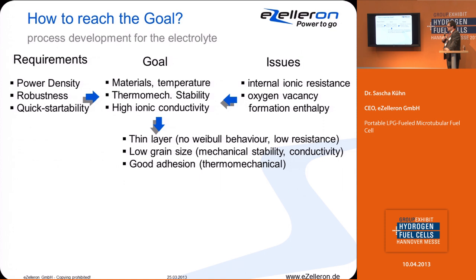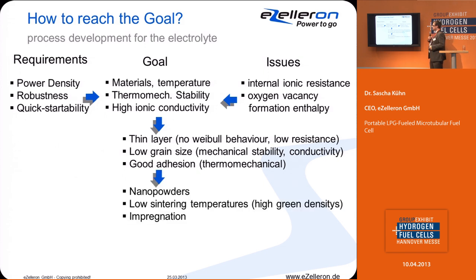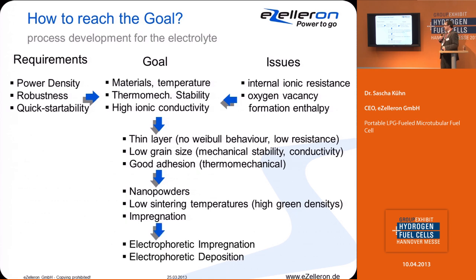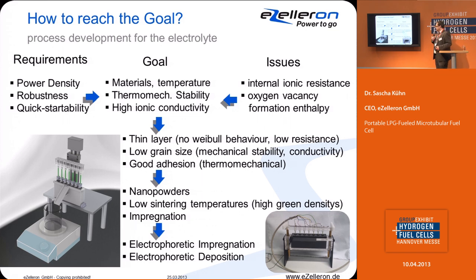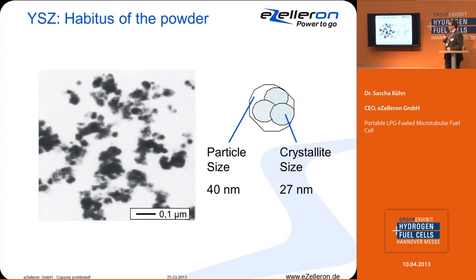The next thing is that for this thin layer you need a very low grain size to improve the mechanical stability. The conductivity of the layer also improves by that, and furthermore you need good adhesion of that layer, because otherwise the layer will crack. This can only be done by nanopowders, very low sintering temperatures, so that means you need high green densities and impregnation processes. So we chose electrophoretic impregnation and electrophoretic deposition to manufacture those layers.